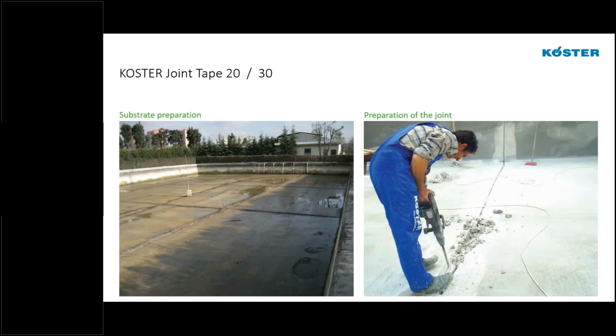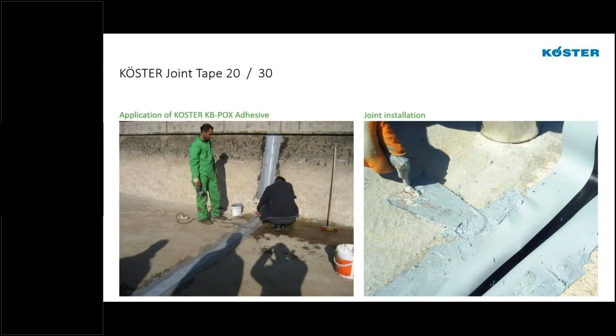Again, so this is, I think, the same installation where we have this big pool where we saw the joint sealant FS, H, and V used. Here, the joints are being cleaned out and any kind of old jointing materials being removed. KB Pox epoxy adhesive, again, is a trowel grade epoxy paste that's used as an adhesive that's installed on the flanks. The joint tape material is then set into the adhesive, rolled or troweled to remove any air and packed into the adhesive bed, and then the adhesive is troweled and brushed over to overlap onto the joint tape.